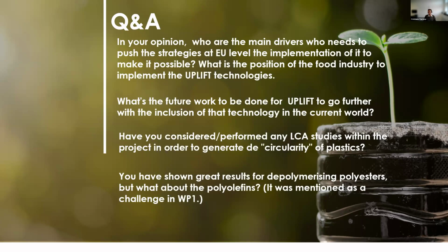And it was also possible after optimization of fed batch feeding strategies to come up to gram scale PHA production out of this. So we changed our original strategy, which was not, I would say, scalable from a process point of view, into this combination with chemical recycling. And this is what we plan actually to work further on, to do process intensification and then scale up, because this seems to be more promising.